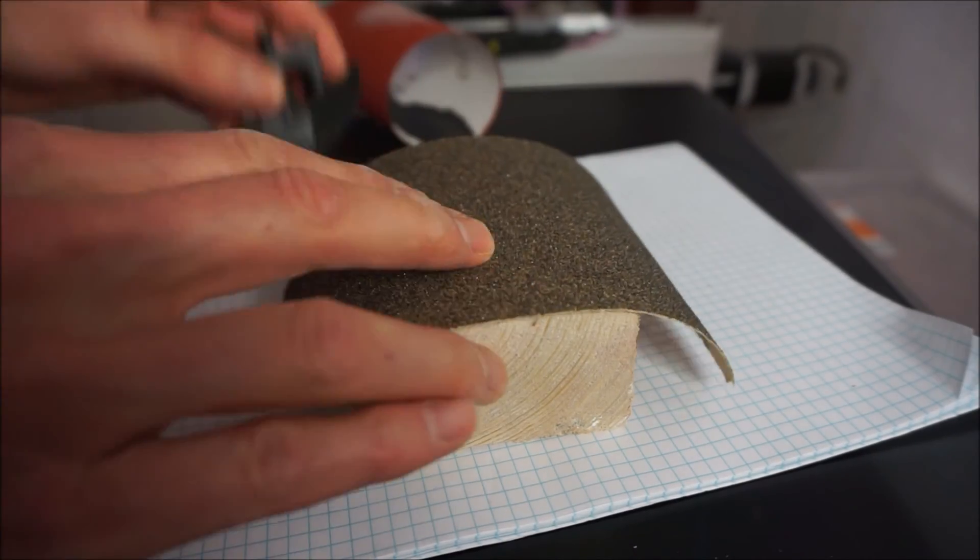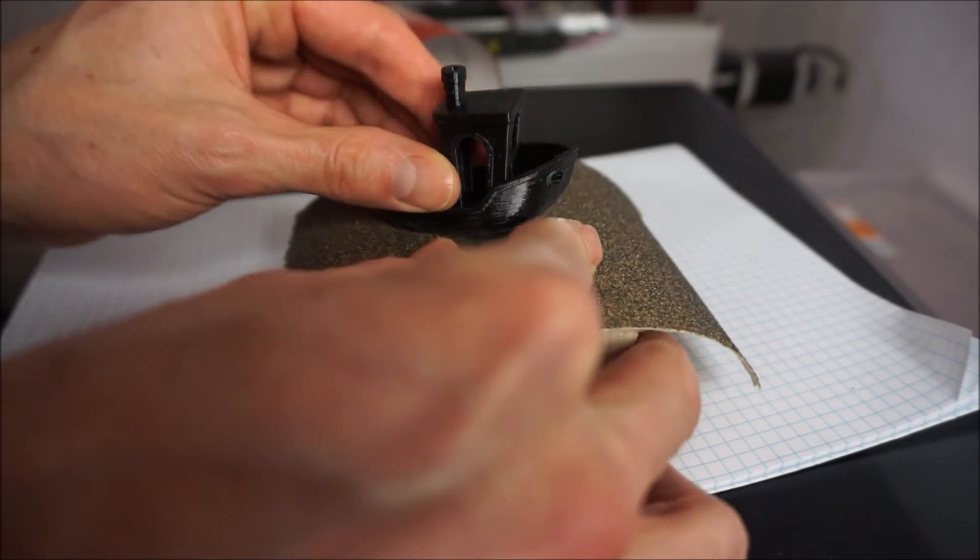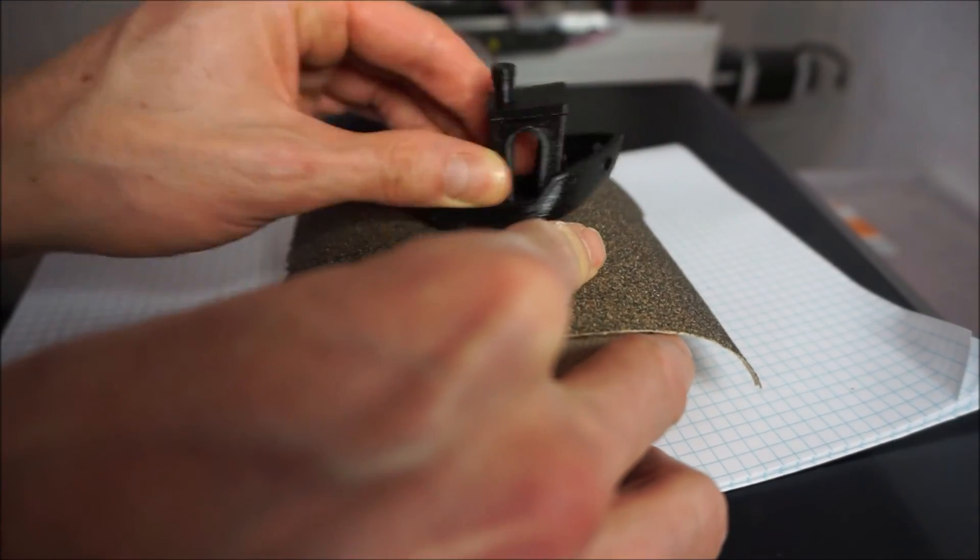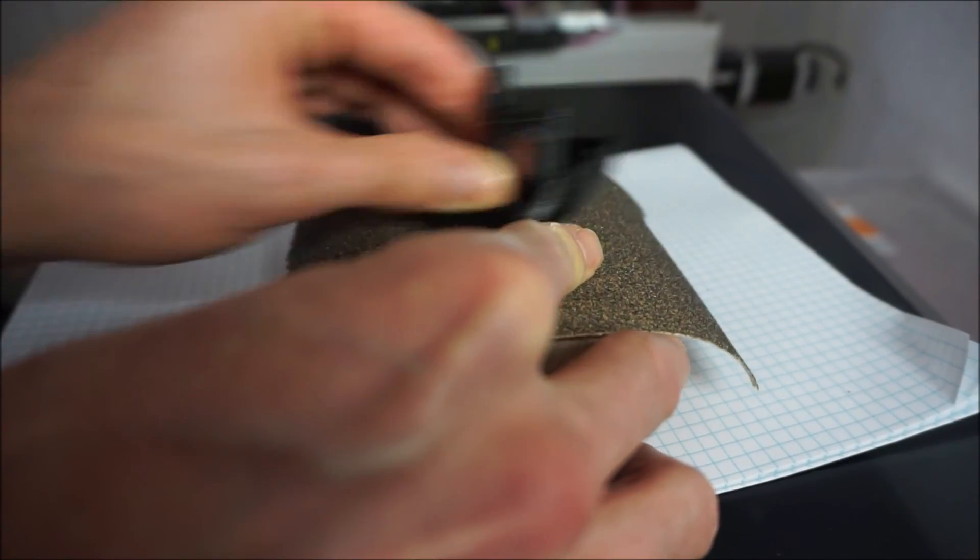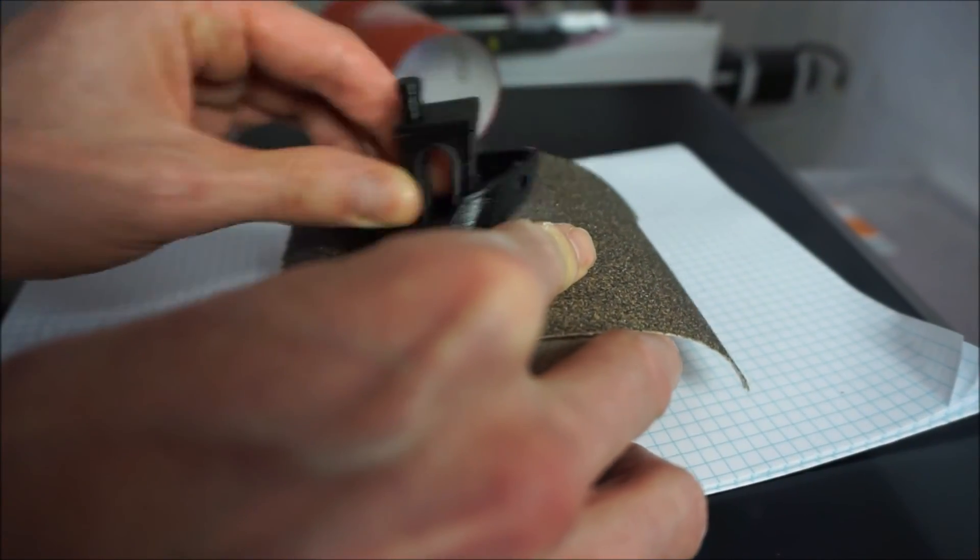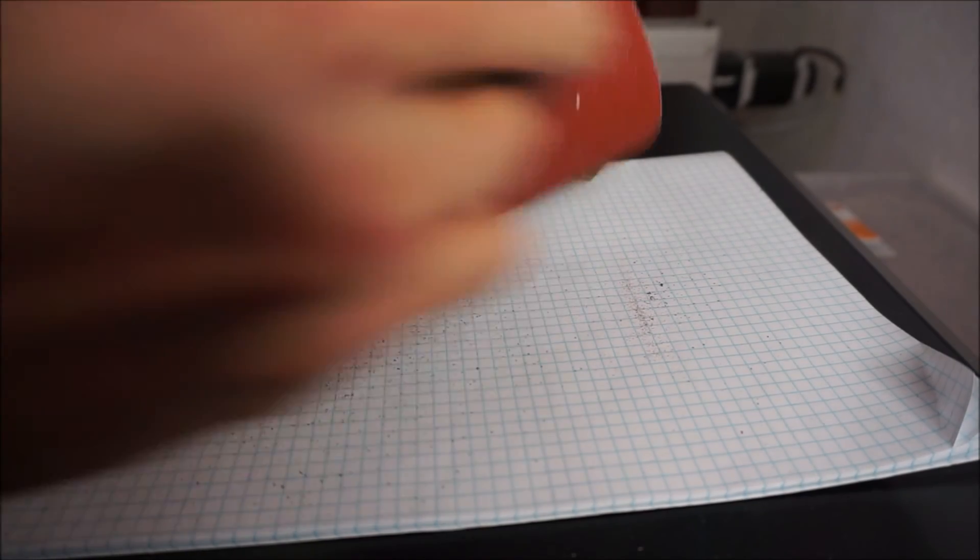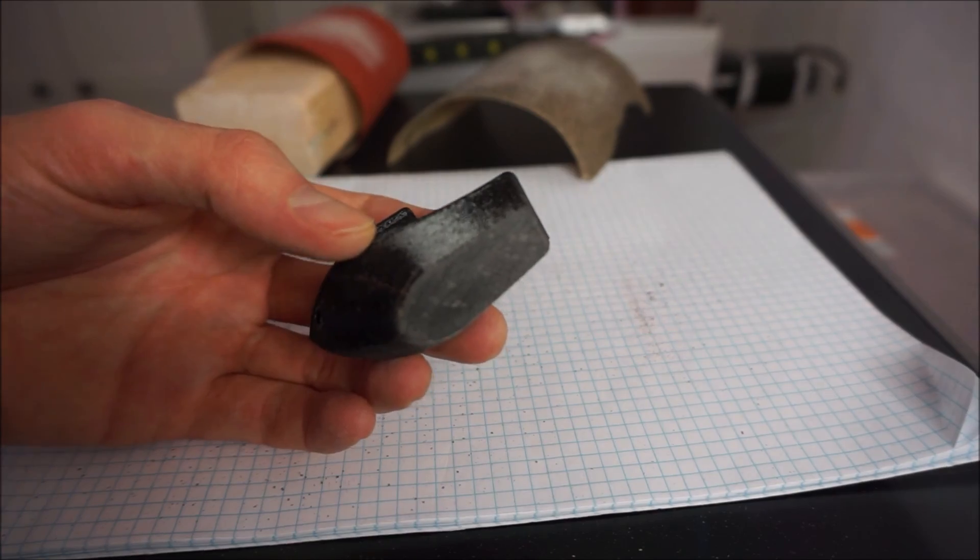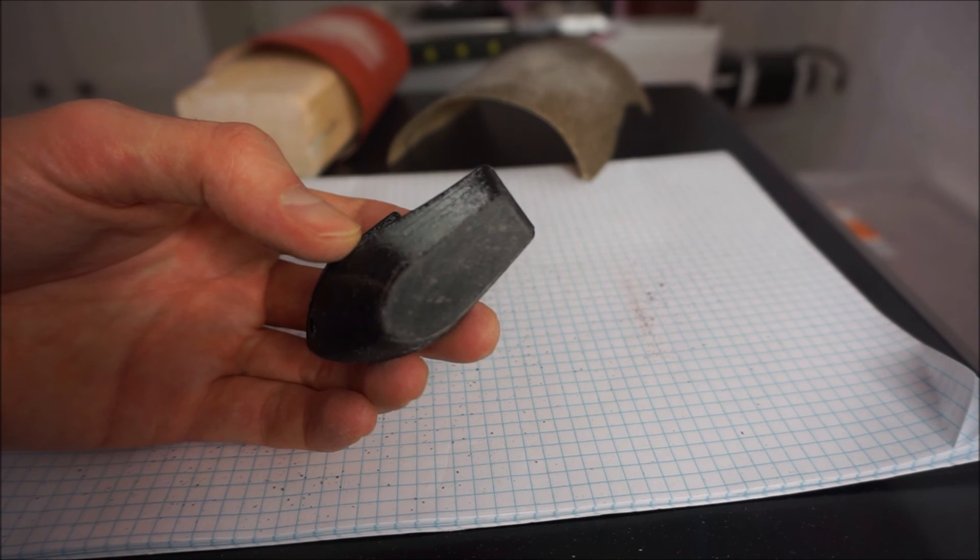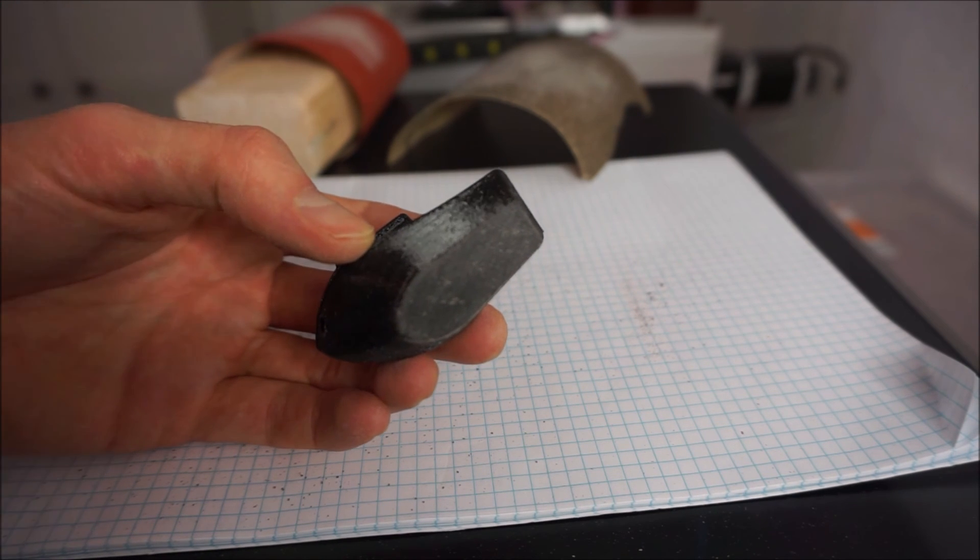After removing the largest portions of the raft by hand I used some coarse sandpaper starting with 60 grit and then moving on to finer sandpaper to remove all of the raft. And it actually left quite a decent finish.